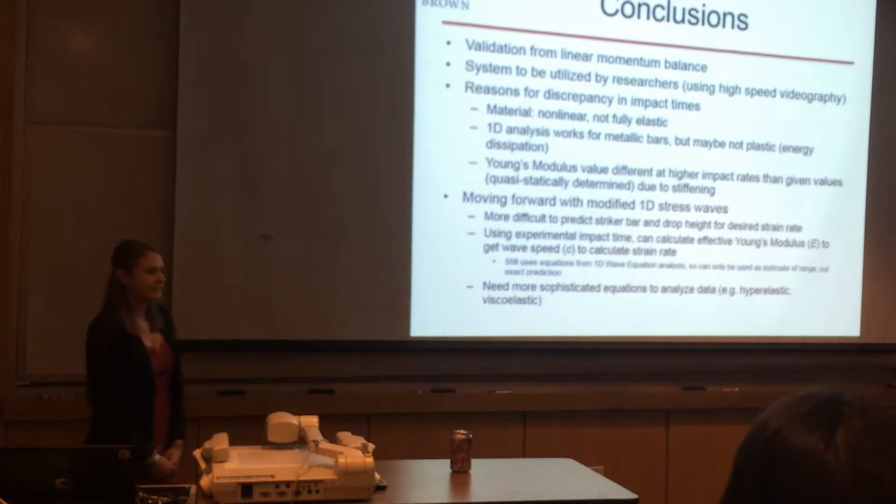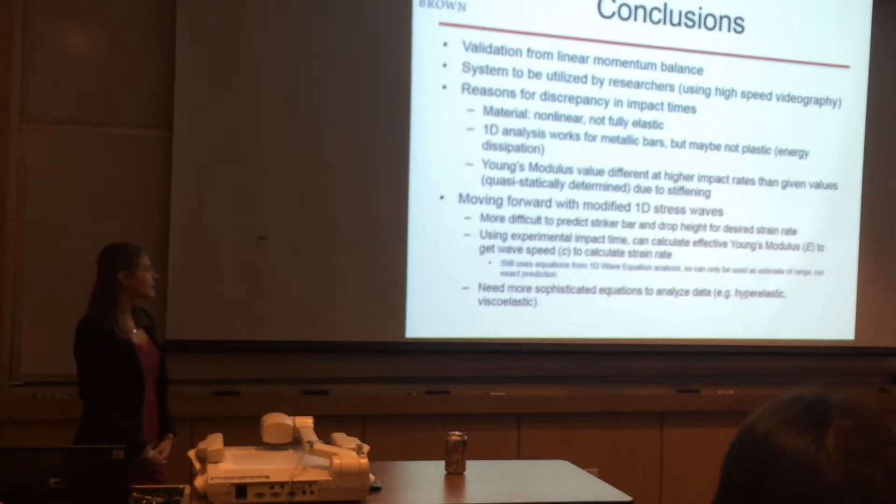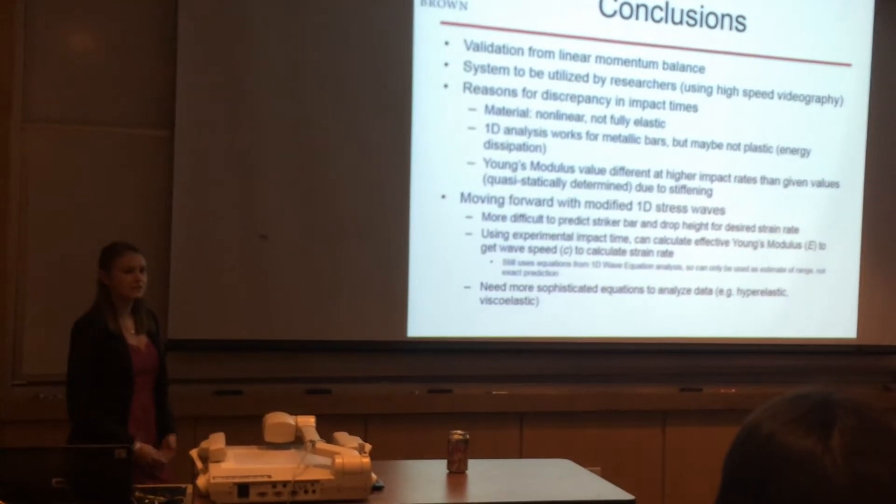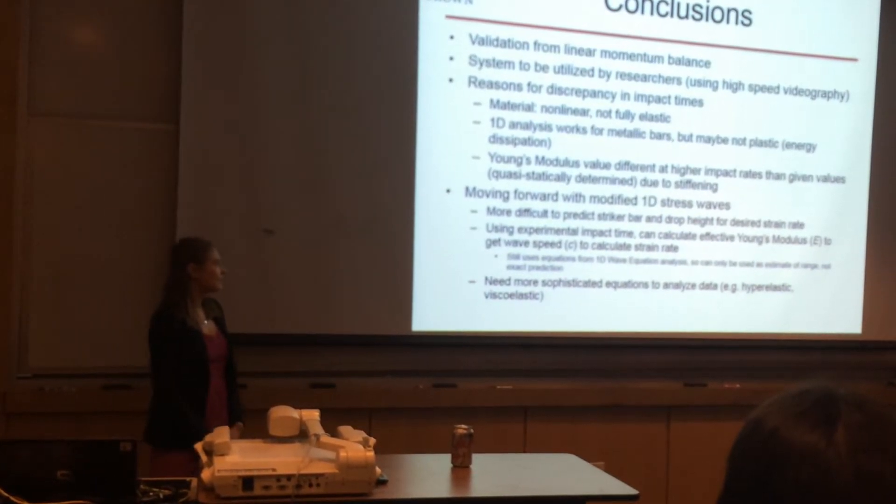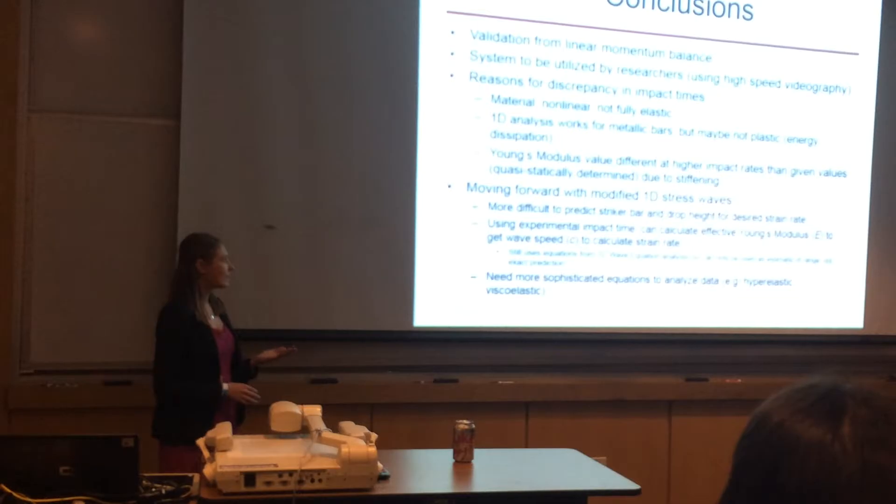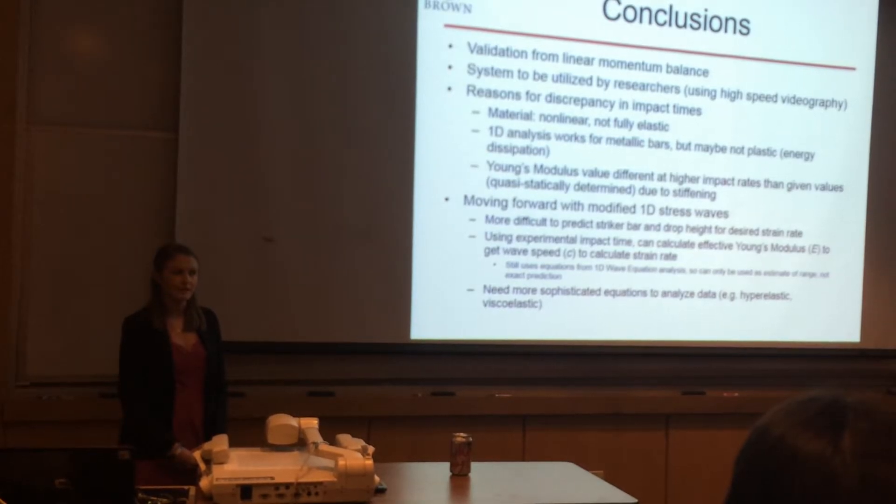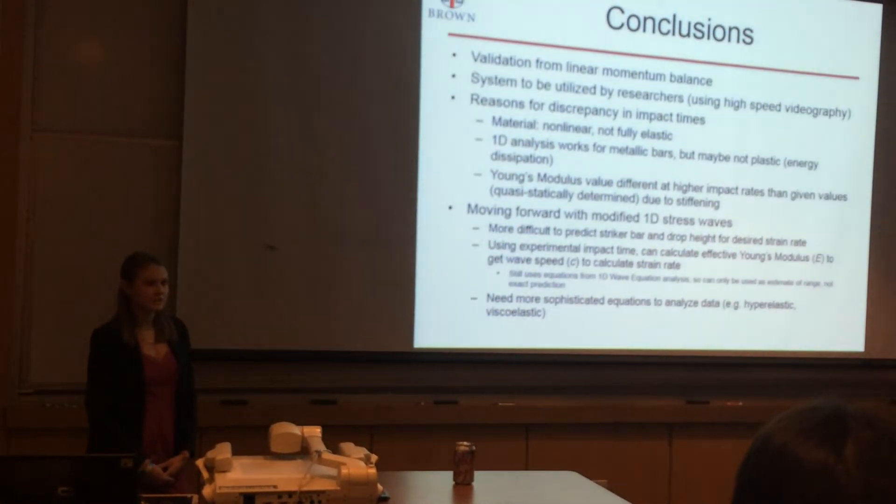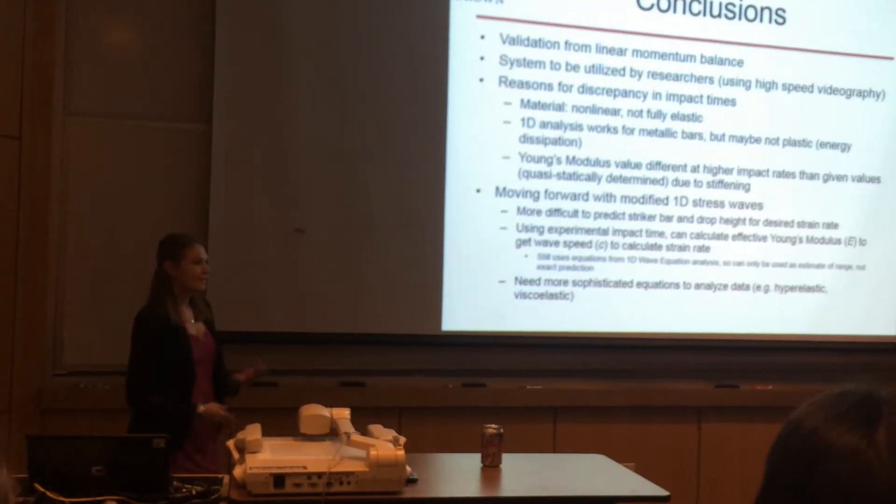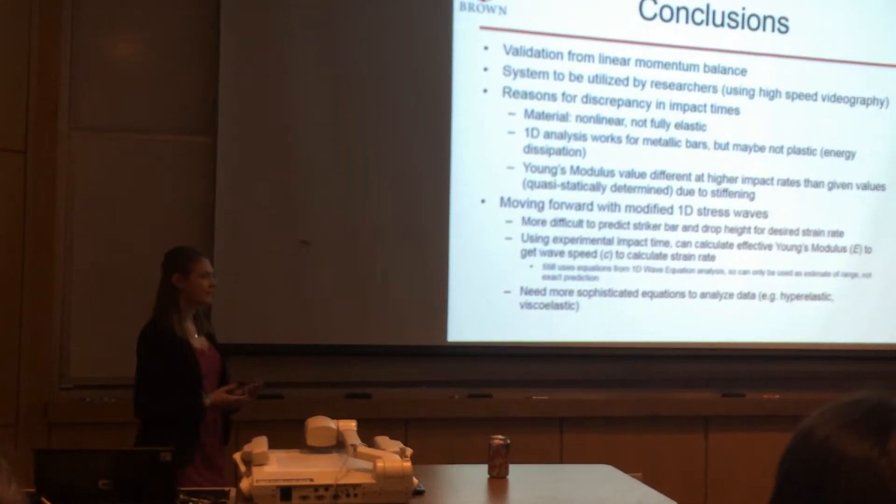In conclusion I had a validation from the linear momentum balance from the way that the impact velocities matched up with little error and the system will be utilized by researchers using high-speed videography as mentioned but yet we still have this discrepancy in impact times. There are several reasons for that. The material is probably non-linearly elastic or not fully elastic. We've seen that this 1D analysis works well for metal bars and has been used in that way but maybe it doesn't work as well for plastic bars due to the energy dissipation. In addition the Young's modulus values I used to calculate the theoretical impact time were quasi statically determined but they may have been different in this case because there were high impact rates so it could have changed the Young's modulus due to stiffening or softening of the material.